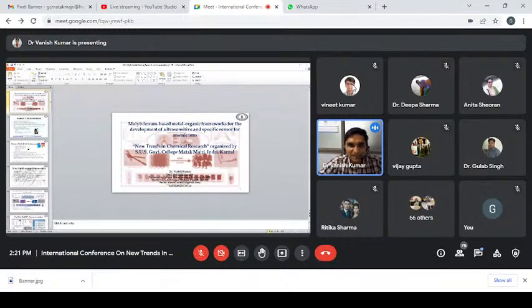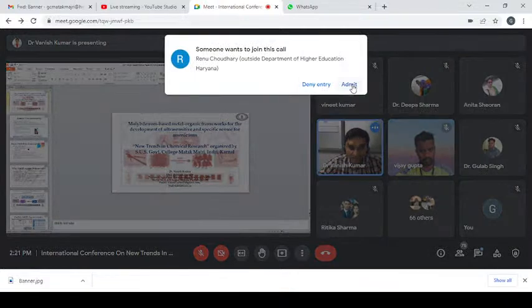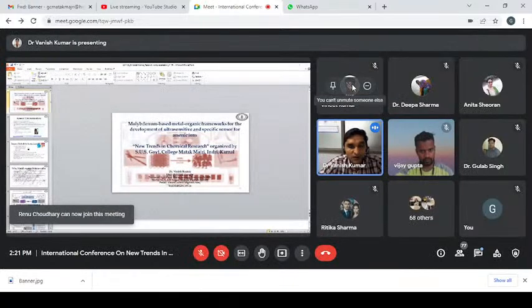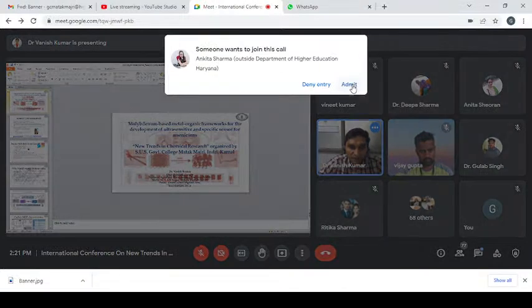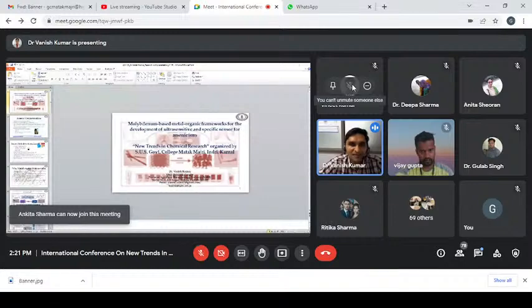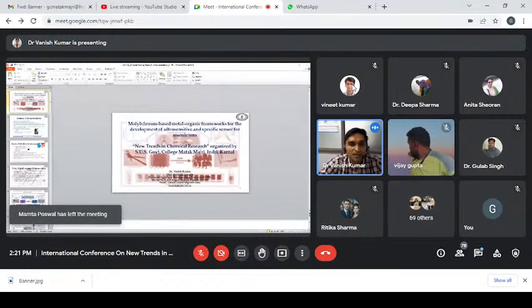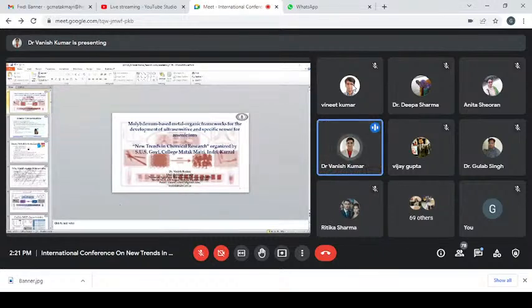So this is a basic scheme of the sensing material and the sensors we developed for arsenic. The sensor is highly specific, sensitive, and selective for arsenic, and we can detect a huge range from 0.05 ppb to 1000 ppm of arsenic using this material. And within 15 minutes, we actually got the final results within 10 minutes, but for safety purposes, so that we don't get false positive or false negative results, we gave time of 15 minutes to this sensor to check the arsenic content in the diverse food products and water, groundwater.